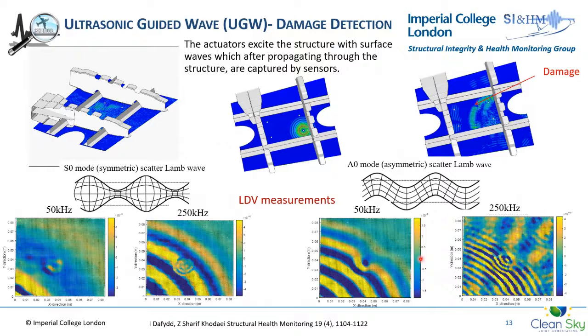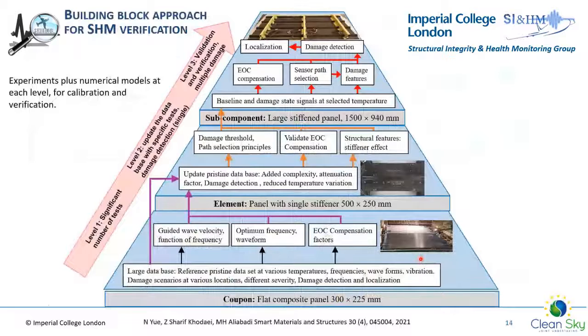So this means that if the guided waves that are propagating in the plate and that you're recording are sensitive to operational conditions such as changes in temperature, changes in load or background noise, these changes can be mistaken for damage if you don't correct for them. So that's why it's very important to study the effect on guided waves, especially of temperature differences, because the effect of temperature can easily be mistaken for the effect of damage.